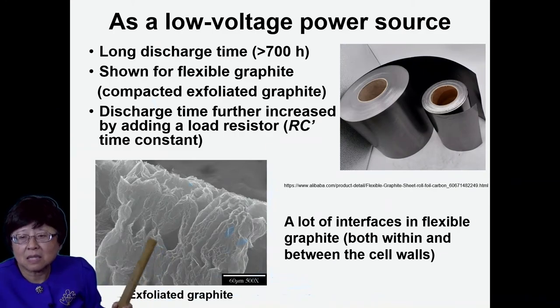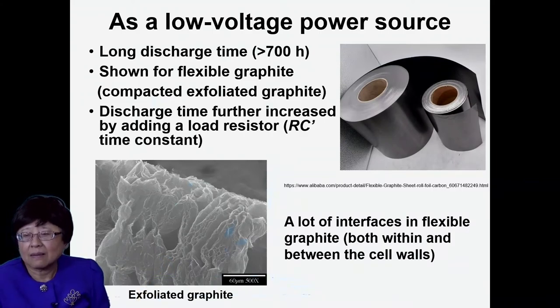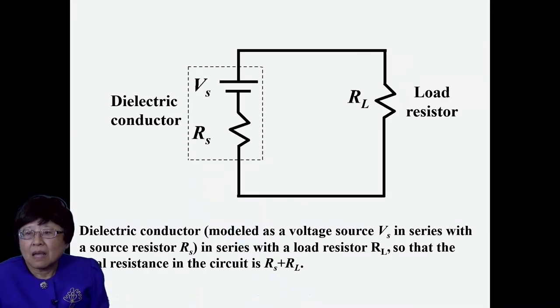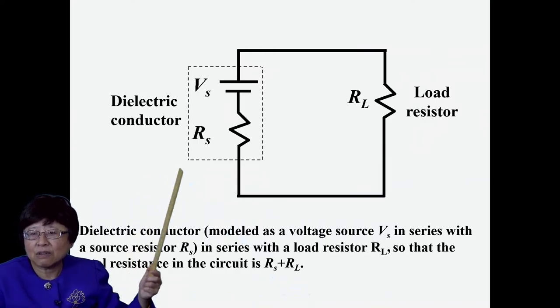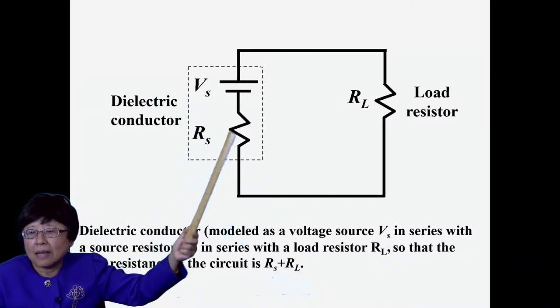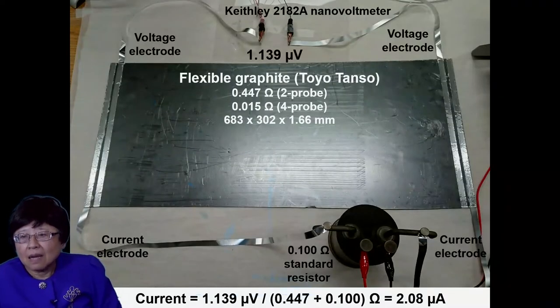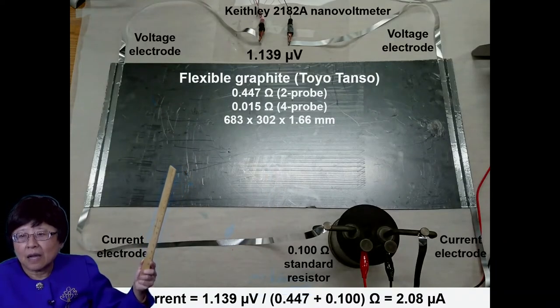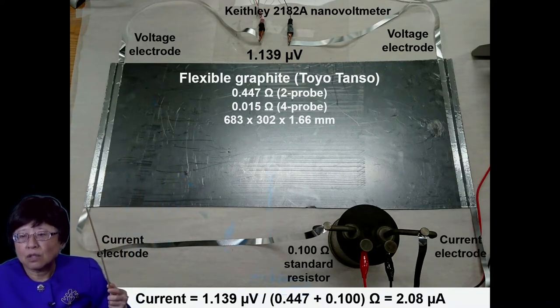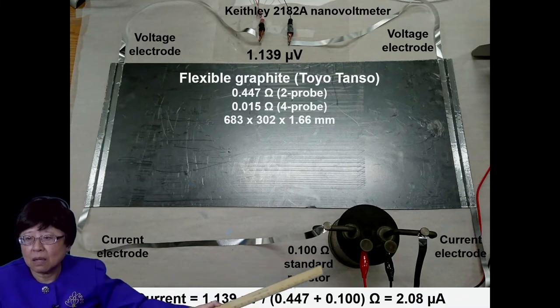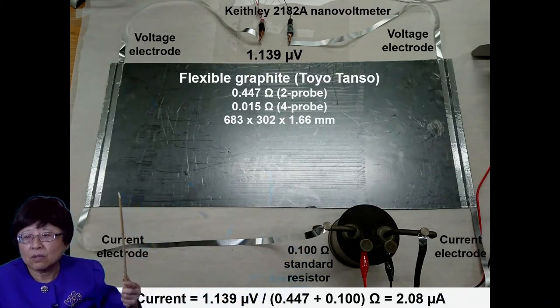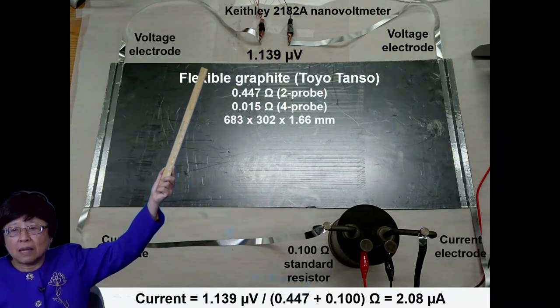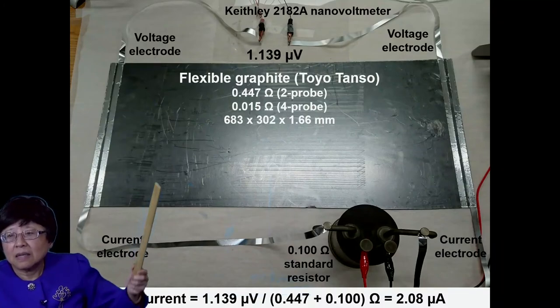The flexible graphite, you can see, has this microstructure with a lot of interfaces, both within and between the cell walls. And I believe that microstructure is responsible for long discharge time. So I envision having the dielectric conductor acting as a power source and a load resistor, R sub L. This is the flexible graphite commercially available, a sheet, and I have the two outer electrical contacts in the form of aluminum foil and silver paint connected to an external load resistor, and then the two inner contacts used for measuring the electret voltage.